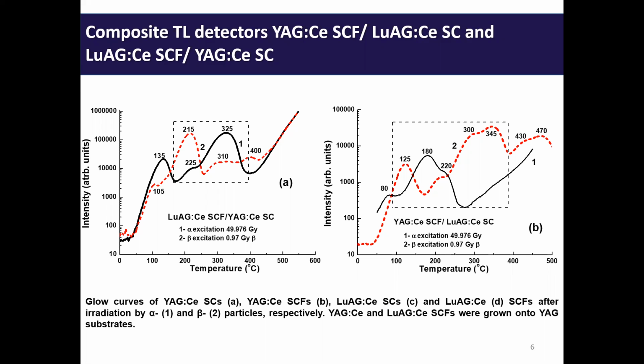In our opinion, the most suitable range for registration of differences in the TL glow curves for these epitaxial structures, composite detectors, lies between 150 and 400 degrees Celsius, where the largest differences between the respective TL peaks are observed for the single crystal film and single crystal part of the composite detector.